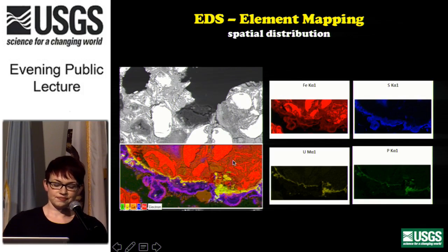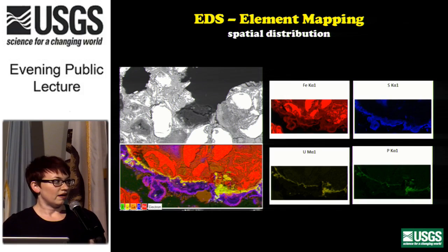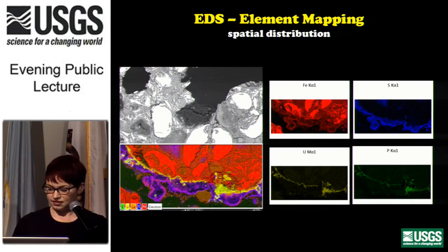This is a USGS project that's looking at groundwater remediation, for groundwater that's been contaminated by uranium, and they want to use iron to try and sequester the uranium. So here we can see the nice yellow uranium rind on the iron. Not only that, but on this composite map, where red plus blue makes purple, we also see a sulfide rind that's also acting to further armor the uranium onto the grain. So here's an example of not only the technique, but the kind of projects that we're applying it towards here at the Menlo Park USGS.